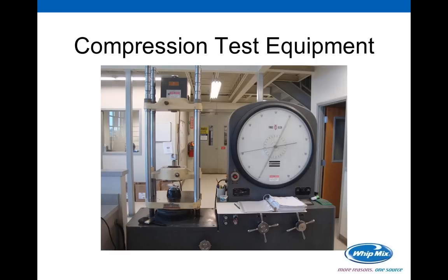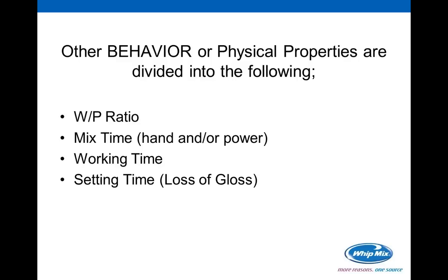Now we do several tests to get a rounded figure, because if we have a little bubble in that piece of material, it's going to be weak at that spot, and it's going to fracture a little bit quicker. So we do several, usually 6 to 8 of those are tested in any given batch to make sure that it conforms to what our standard is. So we do really rigorous compressive testing along with the other testing that goes on here at Whitmix, so that the reported figures that you see on our charts are actual figures that we consistently test to.